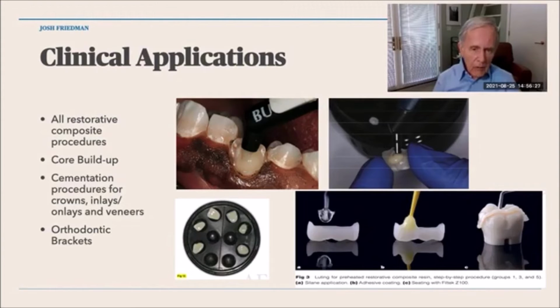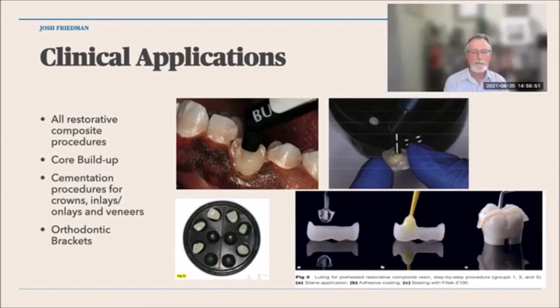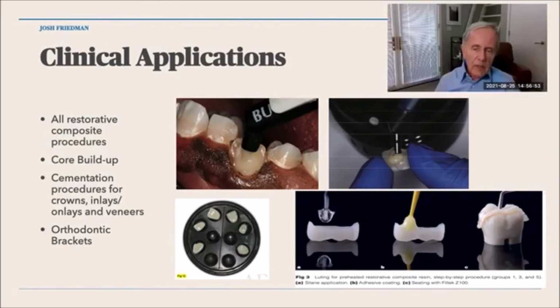They're going to flow as well as or close to a luting cement, but they're not going to shrink. So if you have a margin that has a microscopic space, you'll have a fill-in. You won't have a place where cement can leach out. Years back, I spoke to a professor at the University of Zurich, where they use a lot of CEREC applications for inlays and onlays, and they exclusively cement with light cured cement. And they're doing that for the reasons I've just described.